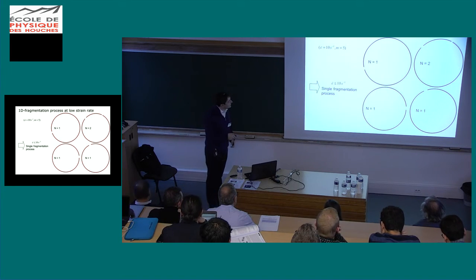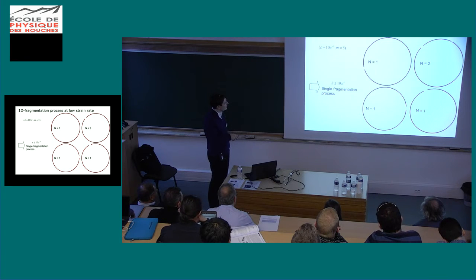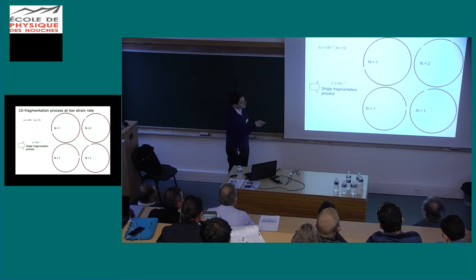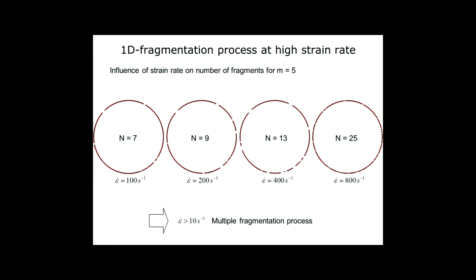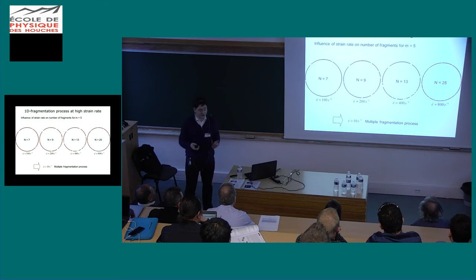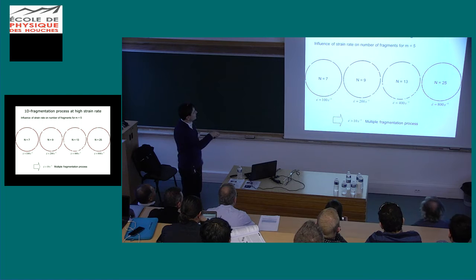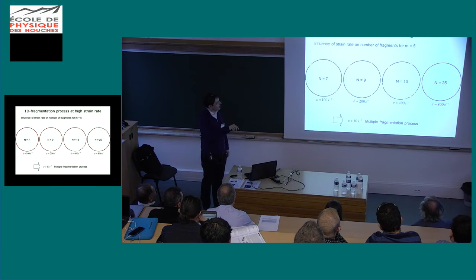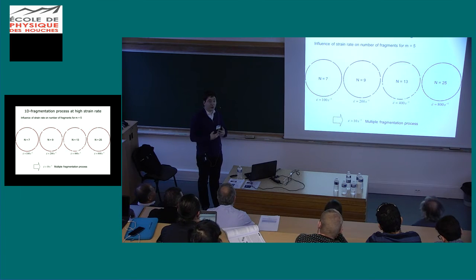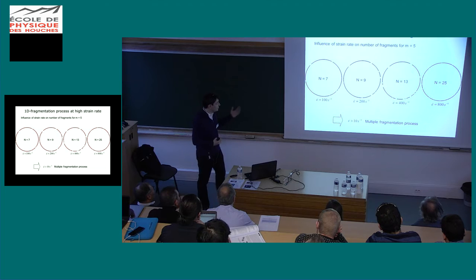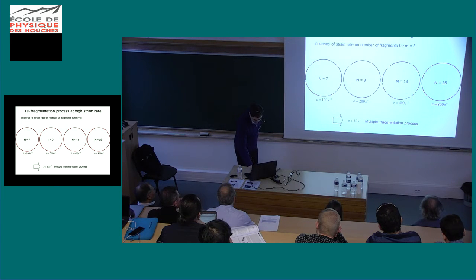What can be observed is that at low strain rate, 10 s^-1, a single fragmentation process occurs, n equal 1, or sometimes we have two failures. Let's increase the level of internal velocity, so the level of strain rate in the ring. At 100 s^-1, now you have 7 fragments. At 200 s^-1, 9 fragments, etc. At 800 s^-1, you have 25 fragments. So you have an increase of the number of fragments with the strain rate, contrary to quasi-static loading. So why do we have multiple fragmentation above 10 s^-1?